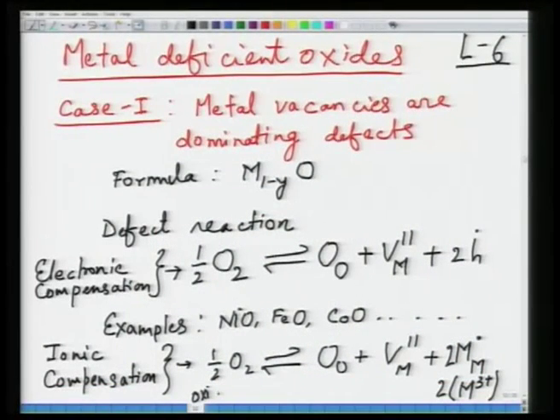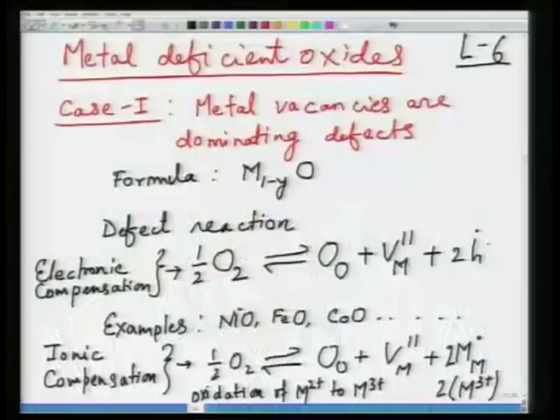So, basically what it means is the oxidation of M2+ to M3+. Now, you can also have M2+ to M4+, in that case only one site will be oxidized. So, this is the basis of ionic compensation and electronic compensation in these materials. Typically, these materials are susceptible to having extra holes. So, metal vacancy is often complemented by creation of extra holes, giving rise to p-type conduction behavior in these materials. Now, we will take the second case.